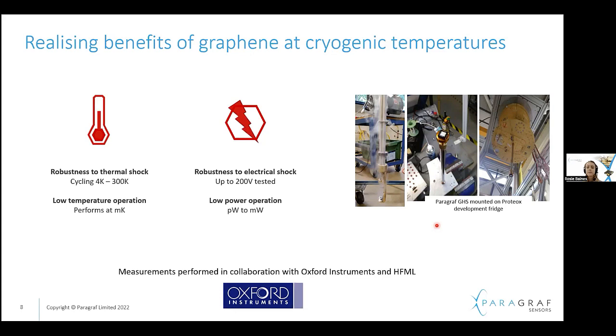Looking at electrical conditions as well, we tested up to 200 volts, and it again showed good robustness and minimal change in performance. Also, it operates at very low power, so we're looking at picowatts to milliwatts, which is obviously ideal for cryogenic applications where minimal heat generation is desirable. But there's also scope to operate at higher currents if that's necessary for the application as well.